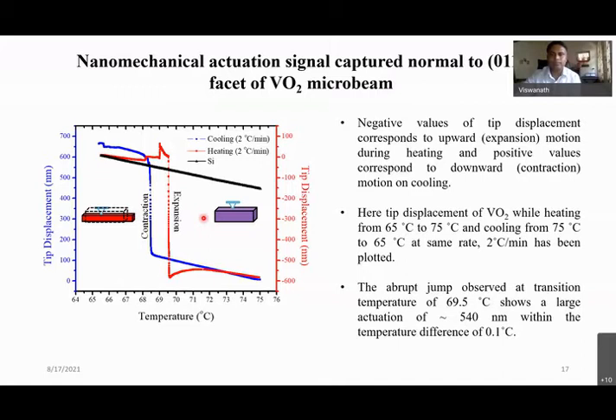So this is a polycrystalline sample. And this is a single crystalline sample. The beautiful single crystal micro beams have, in this case, the orientation of the top surface also 0, 1, 1. And this is freestanding. It is not on silicon. Actually, because of nano indentation, we clamped it on the substrate. Right now it is just for the measurement, to make sure there is no vibration. It is clamped. Otherwise, the crystal can be grown freestanding as well as on the substrate.